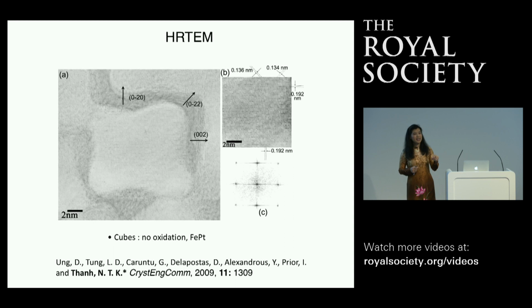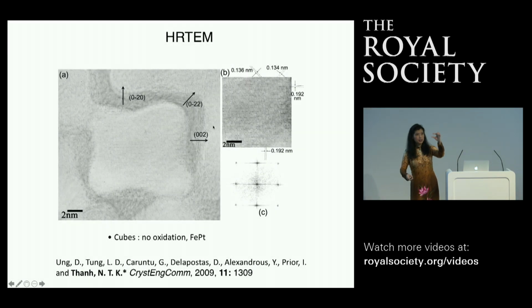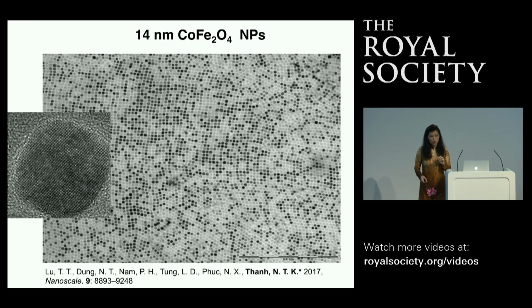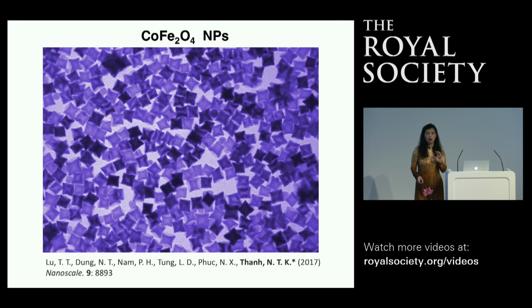We also use high-resolution transmission electron microscopy to look at the particle, because you can see the different atoms here. So by seeing the distance between the crystal lattice, you can determine what phase the particle is. Our aim is to make very monodispersed particles, and we can. But importantly, what's the chemical composition? So this is a cobalt ferrite, and we can also make a very beautiful octapod shape.